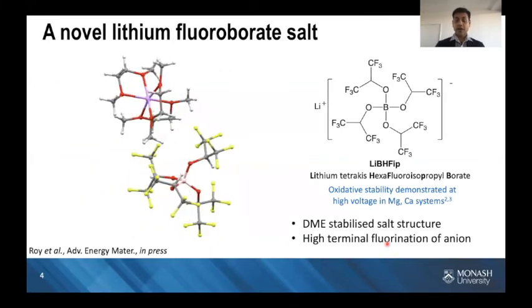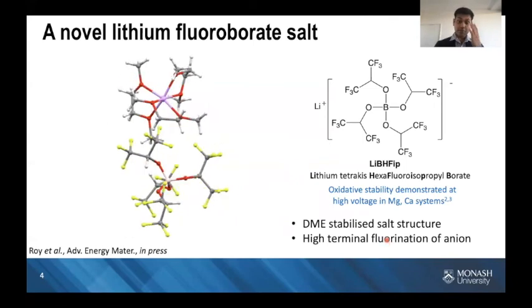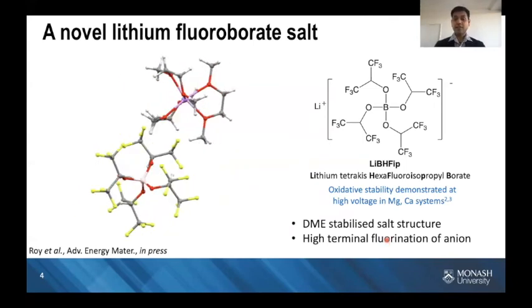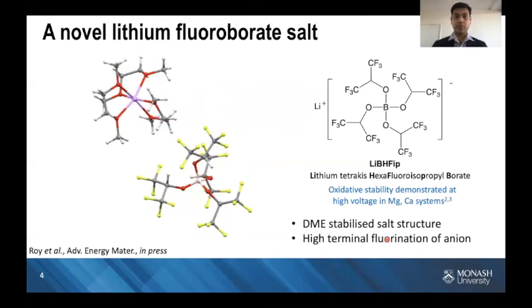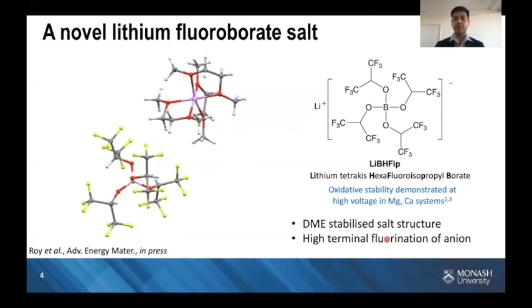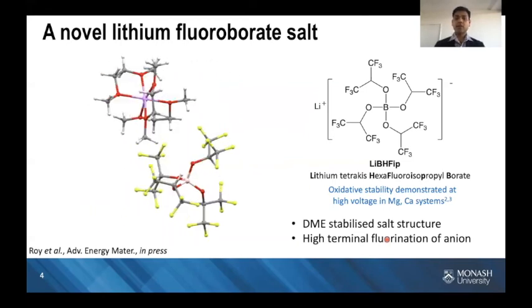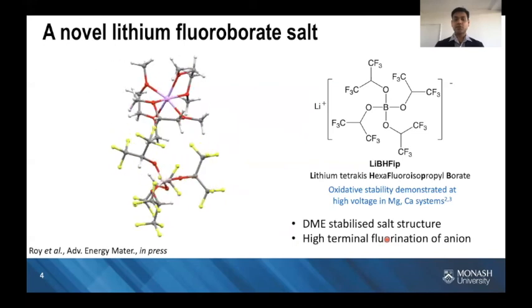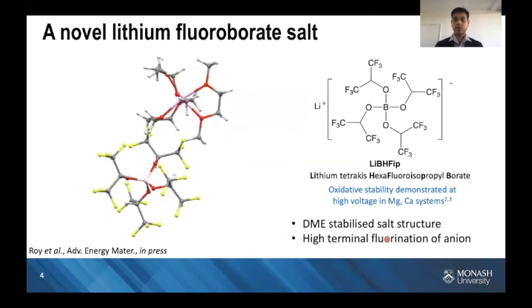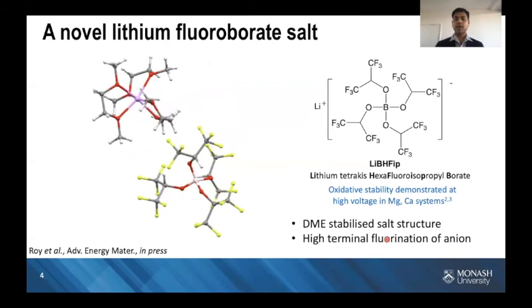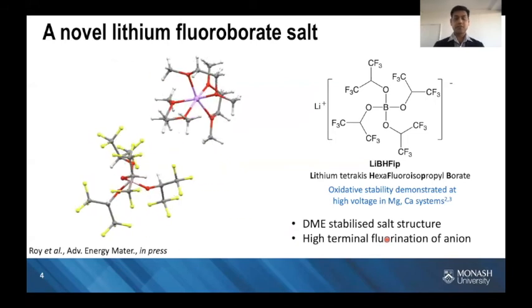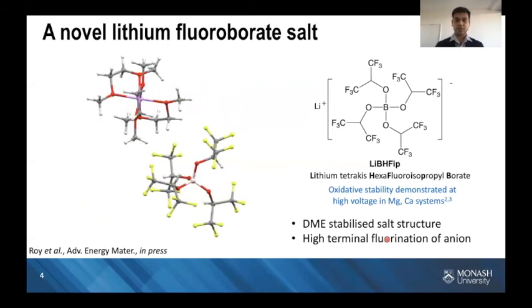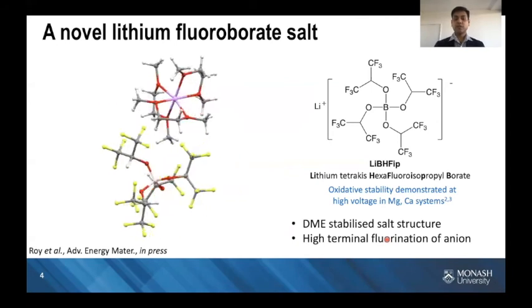In my work, I have found this particular salt to be very interesting. It's lithium tetrakis hexafluoroisopropyl borate, or abbreviated as lithium BHFIP. In literature, it has been shown to demonstrate high oxidative stability with magnesium and calcium systems. However, the lithium equivalent of this salt has not been reported in literature yet.